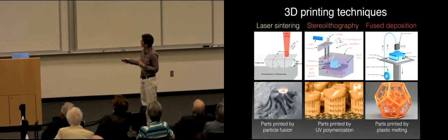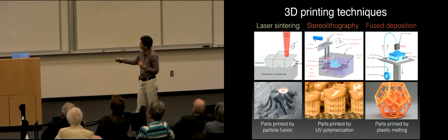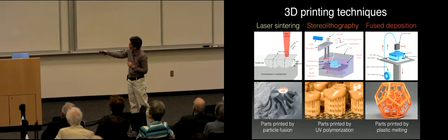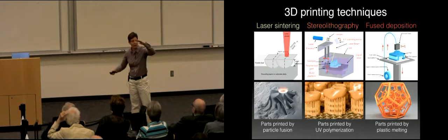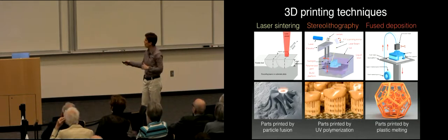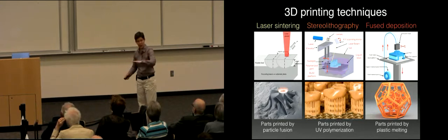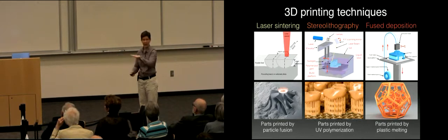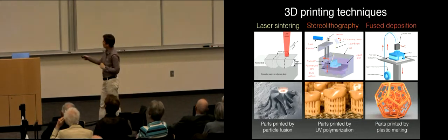So parts printed by particle fusion, you use a very high-powered laser, you locally melt the particles, they re-solidify, and you can build things that are very complex, like this turbocharged rotor. This is a cutaway of this. Here you can see where the laser is impinging and solidifying, and down below you can see all of the subsequent layers that have been previously printed before you get to this layer. So the process goes like this: spread a layer of powder, use a high-powered laser to locally melt where you want the part to be printed, spread another layer of powder, use the laser, and so forth and so on, and build up. These are the in-the-ear hearing aid molds done in a liquid resin.